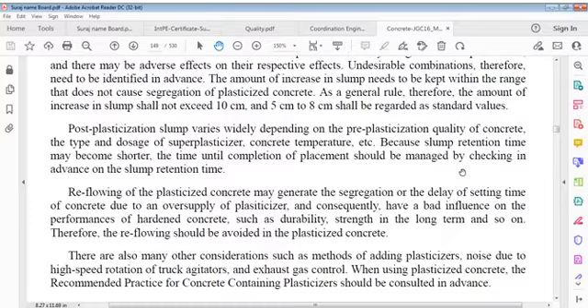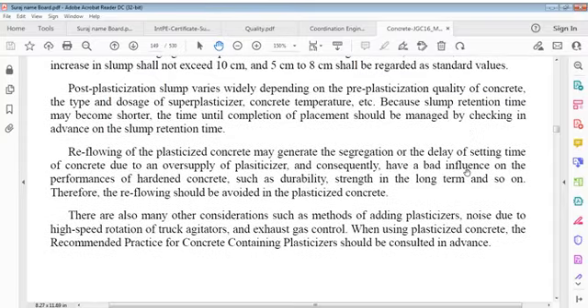That is important, and we have to say undesirable combinations therefore need to be identified in advance. Amount of increase in slump needs to be kept within a range that doesn't cause segregation of plasticized concrete. As a rule, therefore, amount of increase in slump shall not exceed 100 mm, and 50 to 80 mm shall be regarded as standard values.